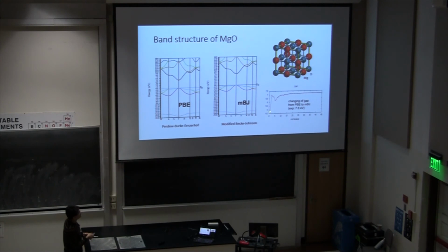This is the first iteration of the calculation. It gives a band gap of 4.5 electron volts. Then in the second iteration, almost immediately the program fixes it and goes to about 7. The band gap in this material is about 7 electron volts. And then it starts playing with it. It goes in the wrong direction, then goes back up in the right direction, and keeps going until the energy gap at n minus the energy gap at n minus 1 is less than, let's say, 0.0001 Rydberg. At that point, the program stops and tells you that's my solution. And you get the correct band structure.